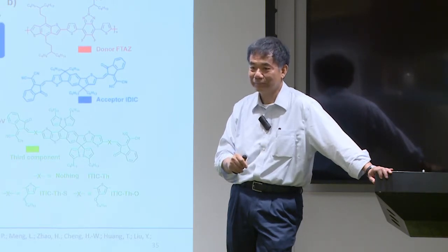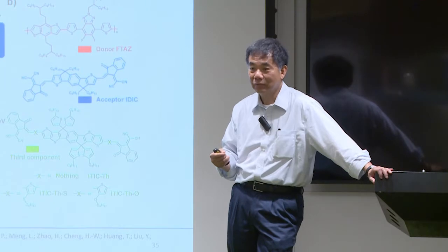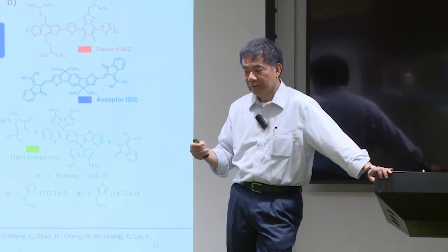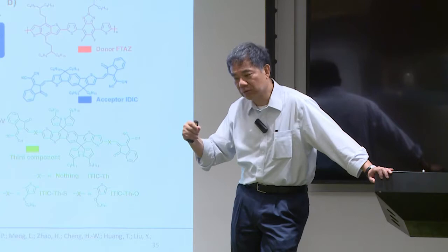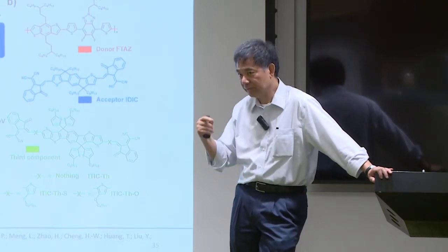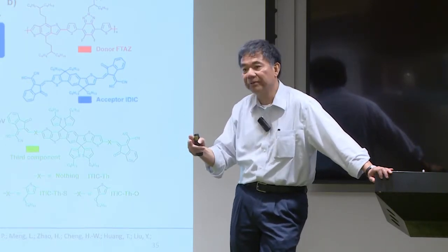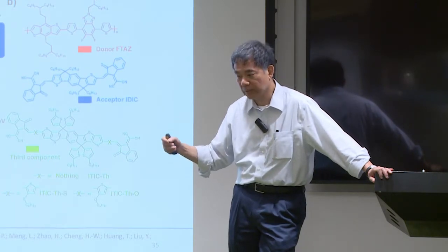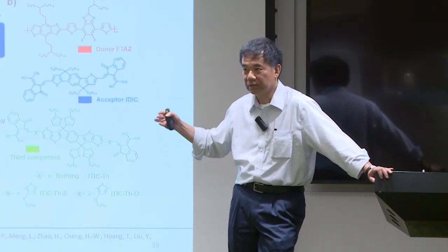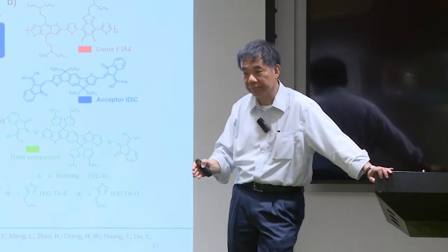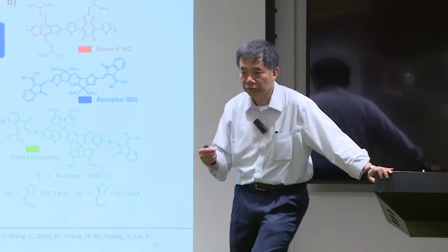But my question is, what's the effect of the 2D perovskite? Let's take the PL data. The PL went up, which means we fixed some of the defects. And the defect could be 1/tau1, tau2, tau3, or could be interface, or the deep level, or grain boundary impurities. And then we saw that the carrier lifetime fast decay component disappeared. The fast component usually comes from shallow defects because they fill the defect quickly.